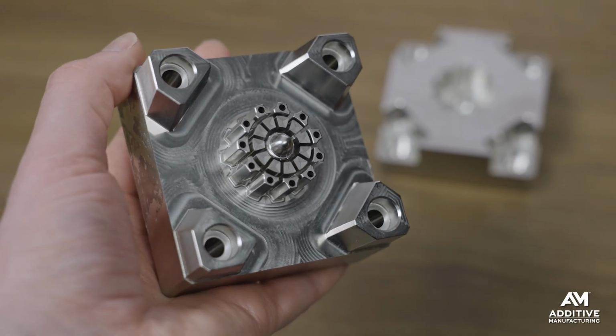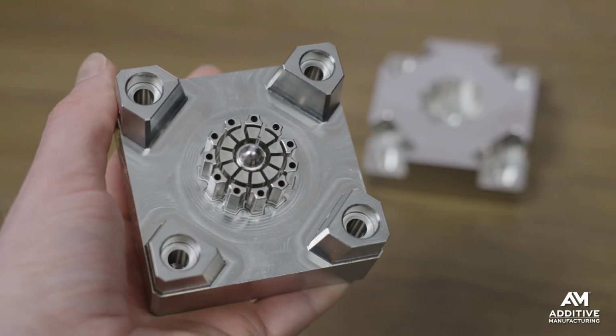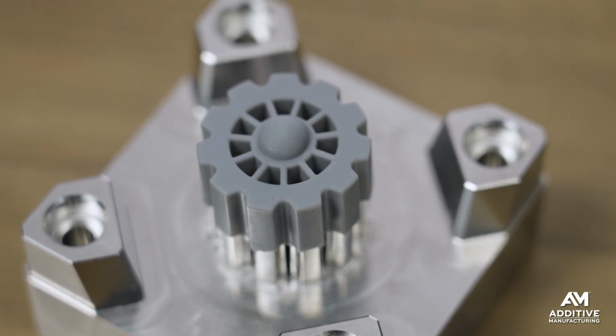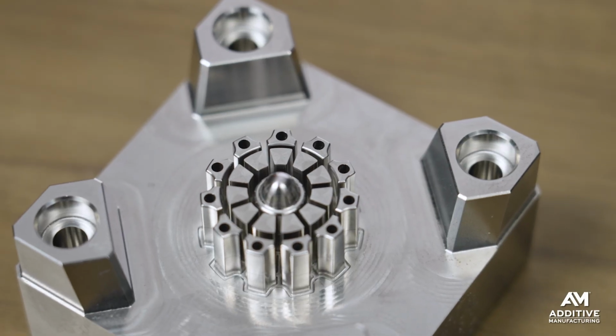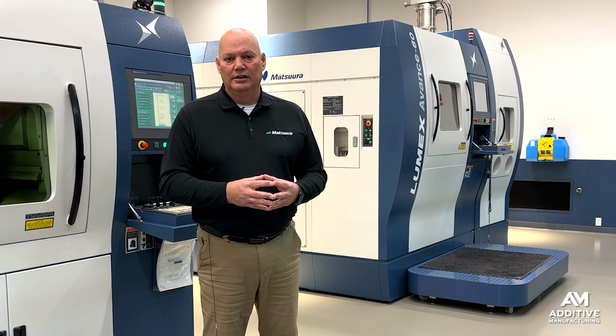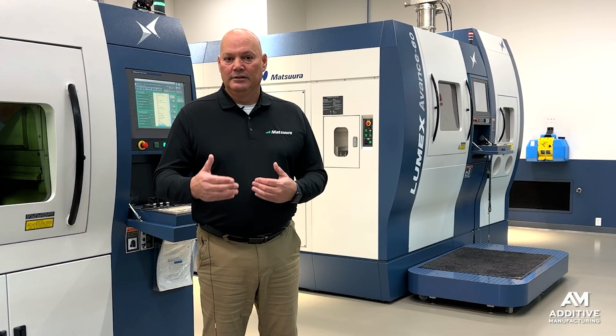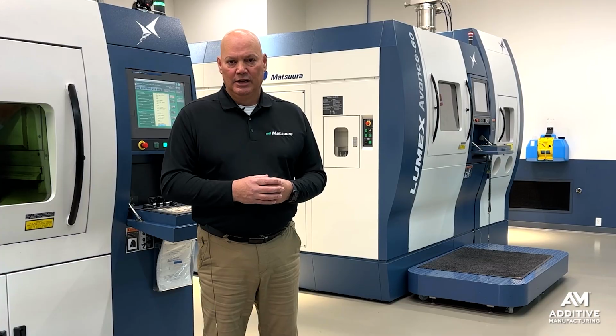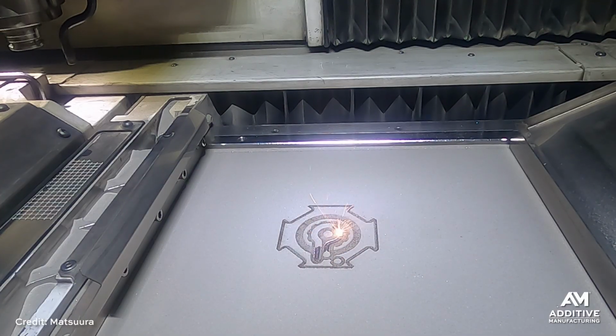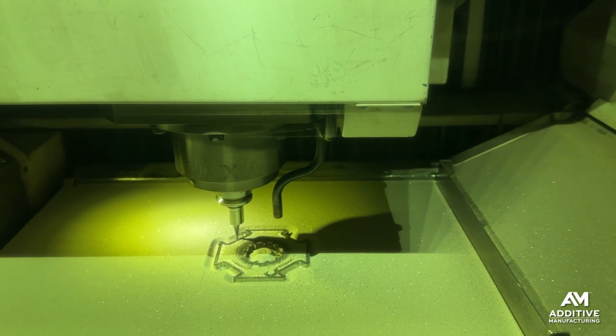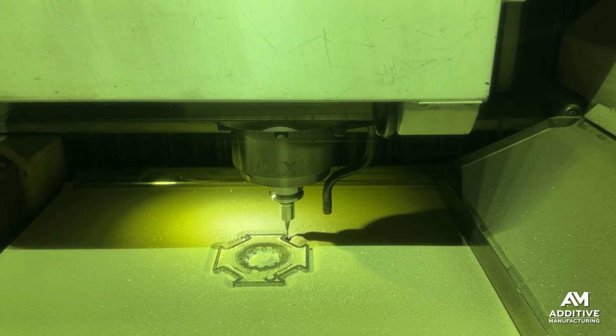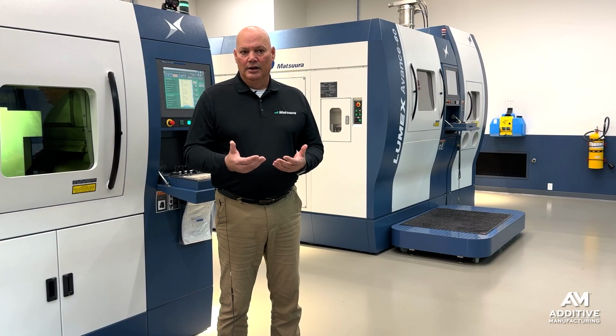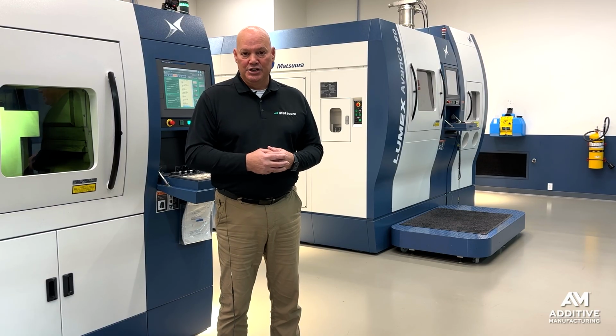In this case, the actual part is used directly out of the machine. So it's 36 Rockwell. Because there's no sliding mechanisms, there's no real shutoffs critical to this part. 36 Rockwell was acceptable to the customer, and that allowed us to use it right out of the machine. Most of the build is done conventionally with our hybrid machining process. So we're doing 10 layers or about 30 seconds of sintering and then about 3 minutes of machining, and then step that as we build the part. Overall, it's about 10% additive and 90% machining.